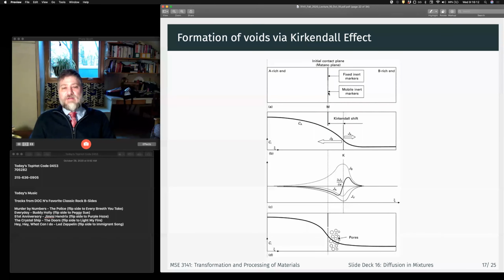the Matano interface, right? And after time, A is going to move into B and B is going to move into A, but they're going to move at different rates, right? So what we have here is a greater flux of B than of A, right? So that means my markers are going to move. If you have an experiment with markers, it's easy to see how far they move. Where the markers are is called the Kirkendall plane. In an experiment without markers, if you just have a diffusion couple, the position that the markers would end up is still called the Kirkendall plane.